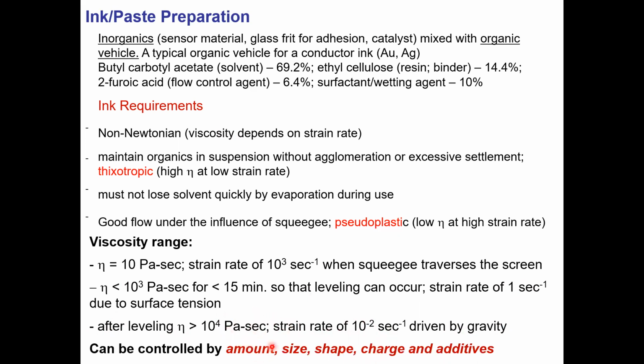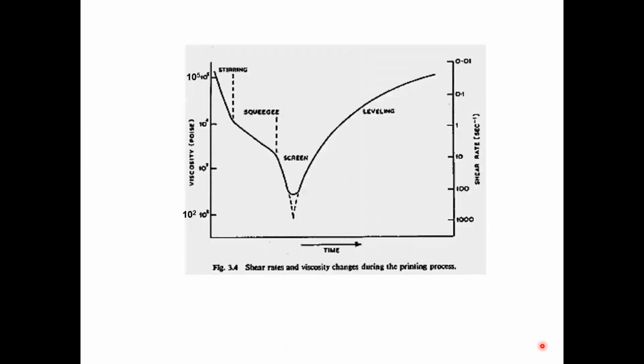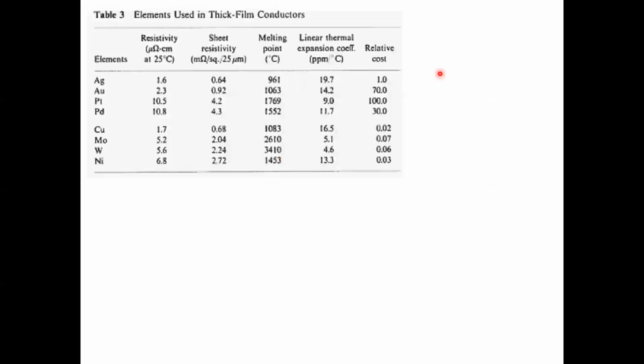The viscosity can be controlled by the amount of solid that you add, their size, their shape, the electrical charge on them, and additives like surfactant and weighting agents that you can add to your ink. So if you look at the typical viscosity values, this is just your ink that you stir for uniformity and so on. And then high viscosity ink. And this is the squeegee that is straining the ink on the screen. And you can see the viscosity drops sharply, and it helps flow the ink through the screen. And after you've done screen printing, then you get leveling. So the viscosity increases, and you get a leveling range to connect the dots, and then eventually it increases so that it doesn't flow any further. So you can avoid bleeding-type behavior.